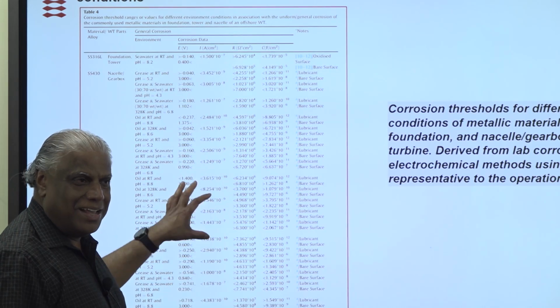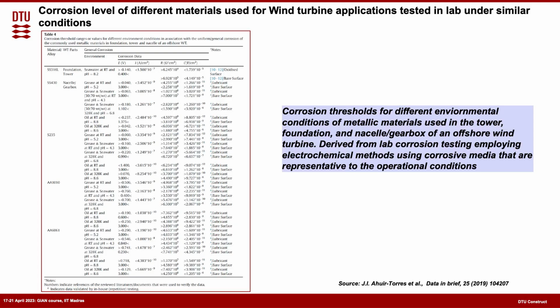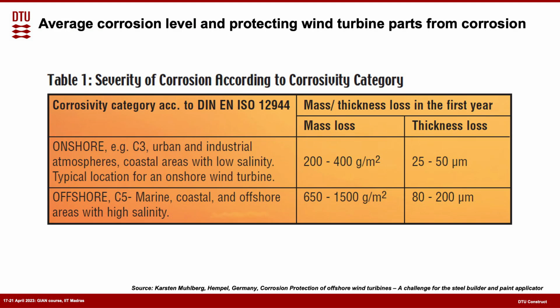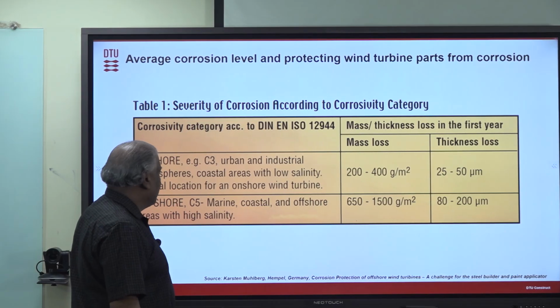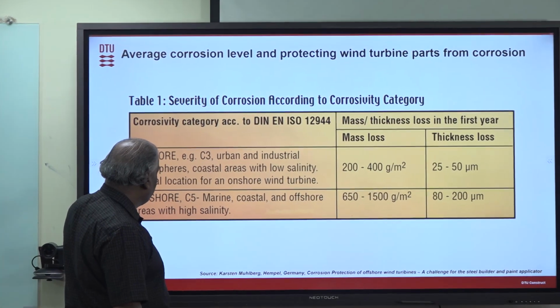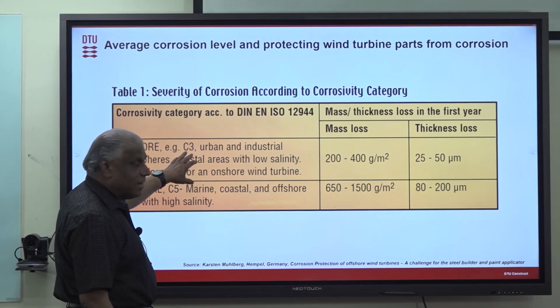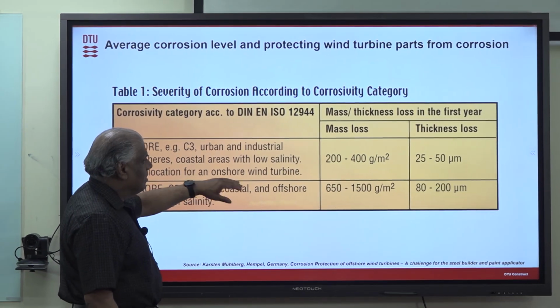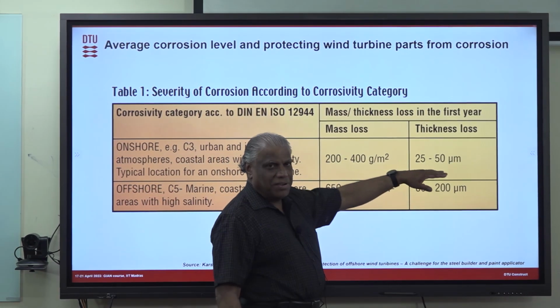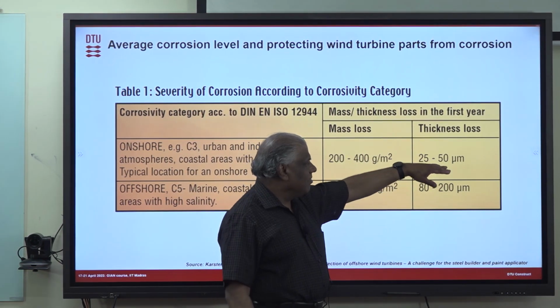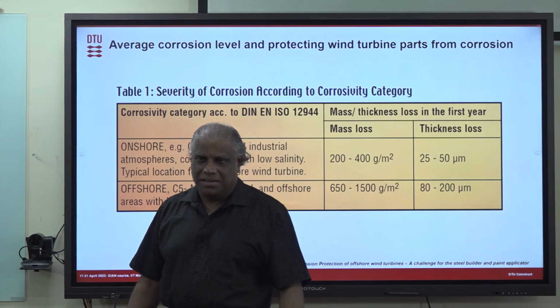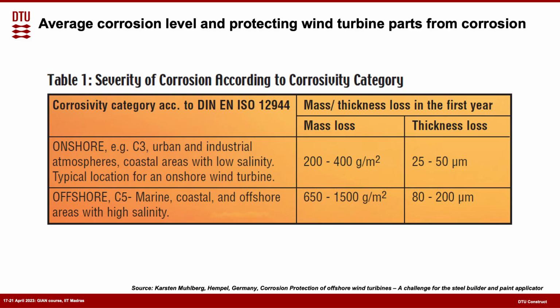I felt that it's quite a nice simulation, exactly simulating that environment in the lab. And they can make a model out of that, and it can be used again to predict something. That means that all these places, you need a very, very high protection level. So this is just showing an onshore wind turbine where you have C3 conditions and the kind of thickness loss. If you take the tower part, the thickness loss you expect is around 50 micrometer per year. That's the kind of corrosion level you expect.